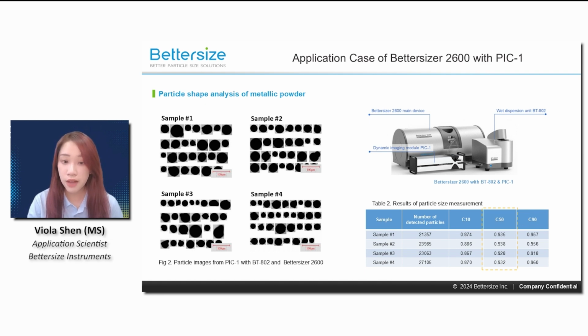So circularity values indicate how closely a particle resembles a sphere, with a value of 1 representing a perfect circle. As we can see, sample 2 has the highest circularity value, suggesting more spherical particles and uniform results, which highly align with the particle size measurements. So with this example, we can see that the Bettersizer 2600 is capable of combining laser diffraction and dynamic image analysis to deliver precise size and shape analysis for the optimization of powder bed fusion process.